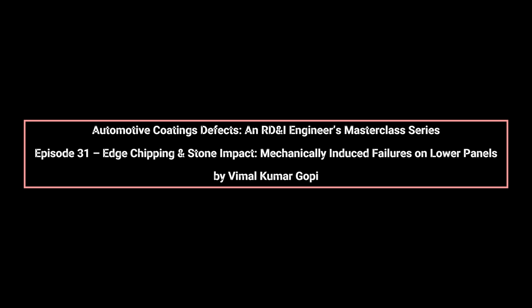preventing these defects. Mechanically induced failures begin at the surface, but propagate depending on the structural and chemical integrity of the coating system. When a small stone or road debris impacts the panel, the coating experiences a high localized force. If the clear coat and base coat layers are too brittle, thin, or poorly supported by the primer, the polymer network cannot absorb the energy, resulting in microfractures that rapidly evolve into chipping. Even when the top coat remains intact initially, repeated impacts weaken the polymer chains in localized zones, leading to cumulative damage. Film build is a primary determinant of resistance.